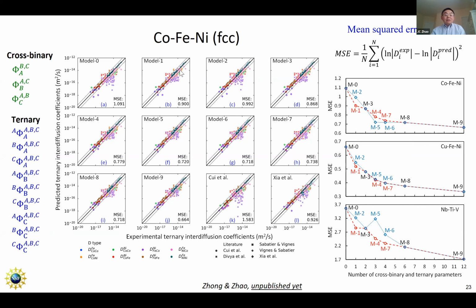And then this model 1 is where we have all the 3 cross binary terms equal. We just introduce 1 ternary related parameter. You can see it gets substantially better than this. So this is the 3 systems: cobalt iron nickel, copper iron nickel, and niobium titanium vanadium. You can see by introducing 1 parameter, the error of the disagreement is much less. This is a very effective way of making the model better.